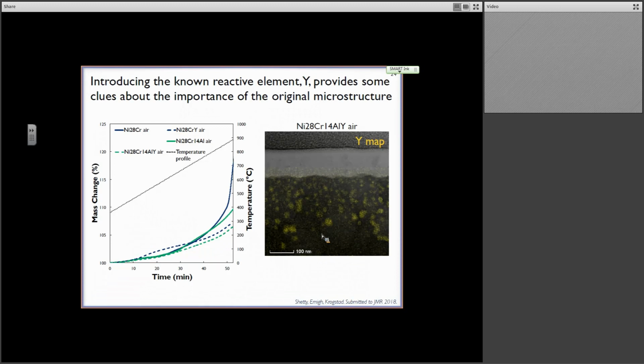Now, as we started, the initial thin films were chemically homogeneous to within our abilities to quantify the chemical homogeneity. There was no chlorine, there was no internal oxidation. And you can see that that's obviously changed. These little yellow clusters were not there before. These are all little yellow yttrium clusters. There's also yttrium incorporated into the oxide scale. That's actually what we had expected. The literature tells us that these reactive elements should go into the oxide scale. But this whole bit of clustering down here was rather puzzling to us.